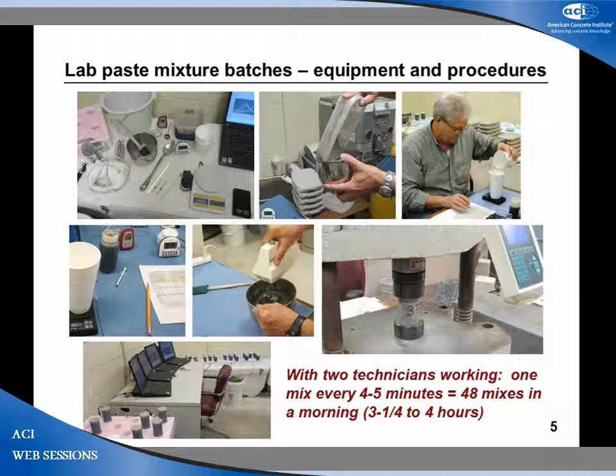This is way better if you're using realistic concrete water cementitious ratios, because that paste becomes fluid and pourable, which is very useful in the process. We pour it up into 2x4 cylinders. We document the thermal profiles overnight. The next day, we'll take one of the cylinders in each case and do a compressive test, sort of a modified C39 type test. And with two technicians working, we typically do a mix about every 4 to 5 minutes, which means in a span of a pretty easy morning, you've got 4 dozen mixes under your belt.